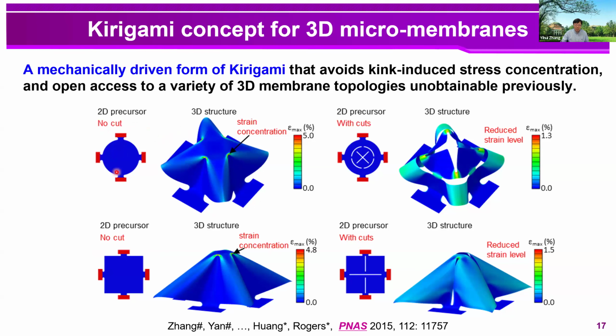For example, if you assign 4 bonding pads uniformly at the boundary of a circle or a square, there will be evident localized deformations in the central area of the structure during the compression process. And this will lead to strong strain concentration. As you can see here, the peak value of the strain already reached around 5%. So in this case, if you use single crystal silicon to fabricate, it will break.